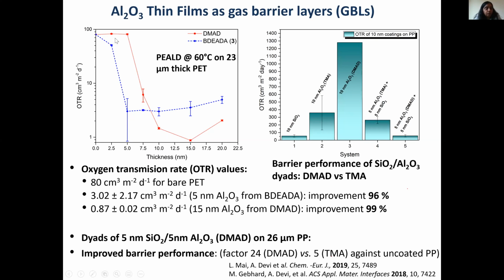And in the case of the other precursor, we compared two precursors here with a similar ligand system, but varied the combinations. And I have some certain terminologies which you don't have to know about, because it's just a fancy name. But when we had the two precursors, we saw that the precursor 3 had the OTR minimum around 5 nanometers.